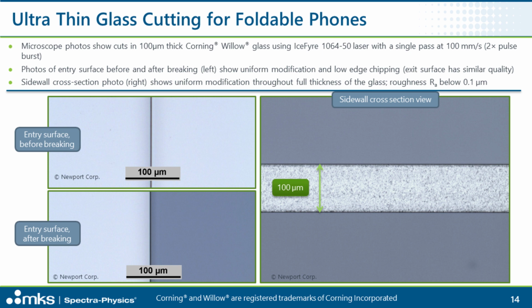And then the sidewall roughness, here we see the 100 microns thickness, and the actual roughness in this case was measured at less than 100 nanometers, and we tend to see 60 to 80 nanometers sidewall roughness. So very low roughness. When you look at it with the naked eye, it actually has almost a polished appearance. With conventional glass cutting, you'll typically see a frosted appearance, but once the roughness goes down below 100 nanometers, it looks quite polished, and we believe that this could reduce the post-processing time required for cleaning up the edges of that glass for downstream processing, such as actual assembly of the mobile device that it may be used in.